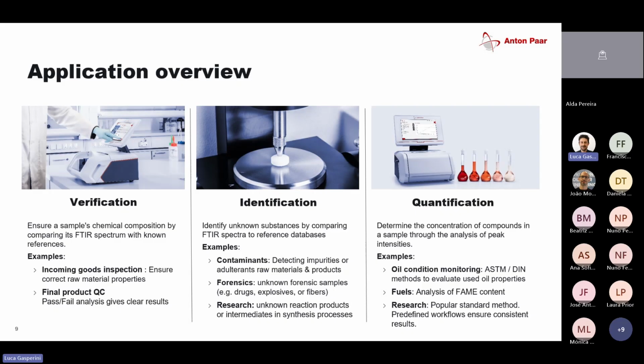And then last but not least, and this is something a lot of people are not really aware of, you can also quantify things. For example, you can quantify filler content in your polymer formulation. A general rule of thumb is that the detection limit of FTIR is 1%, but as always, there are some exceptions. There are also some things which absorb a lot of IR light. There you can also go down into the ppm range.